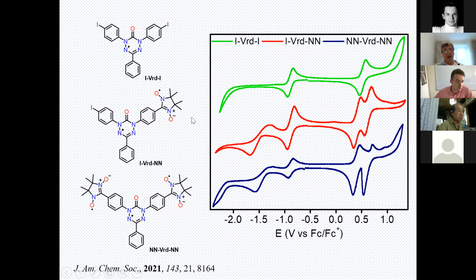As to cyclic voltammetry, if you look at the corresponding curves for monoradicals, diradicals and triradicals, you see that in all compounds we have a reversible, or quasi-reversible in triradicals, oxidation peak related to oxidation of verdazyl blocks, and also a reversible peak corresponding to reduction of the oxo-verdazyl moiety and a quasi-reversible reduction of nitronyl nitroxide building blocks. So actually we have nice behavior. Using electrochemistry, from these compounds we can generate the corresponding monoradical cation and monoradical anion.